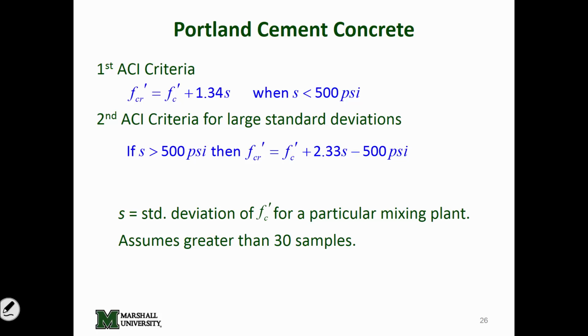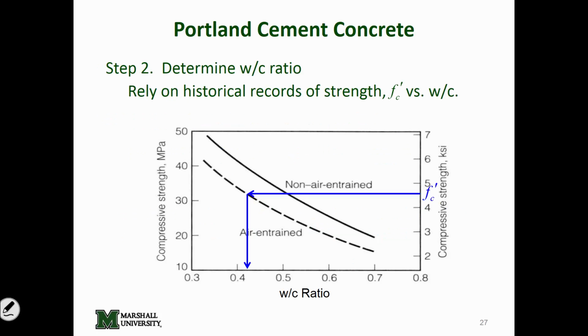Depending on what your standard deviation is, and what equations we're going to use, you want to find your water cement ratio. Somebody says, I want f'c to be a certain value, or f'cr to be a certain value. Go into the simple chart, come over, come down, and that'll tell you what your water cement ratio is. This is a graph that's developed over time in your particular facility.